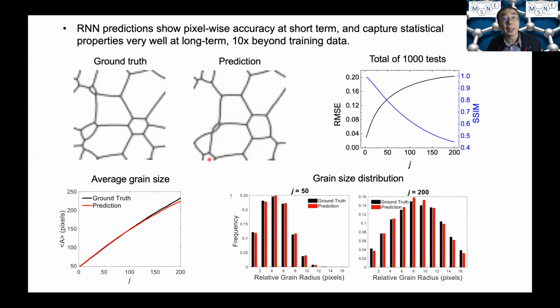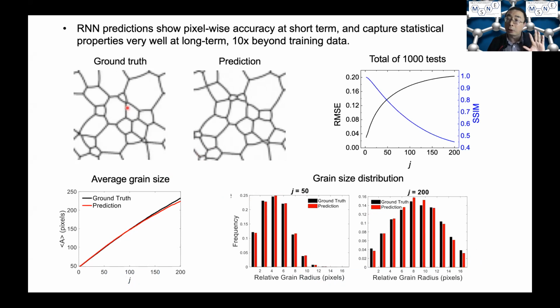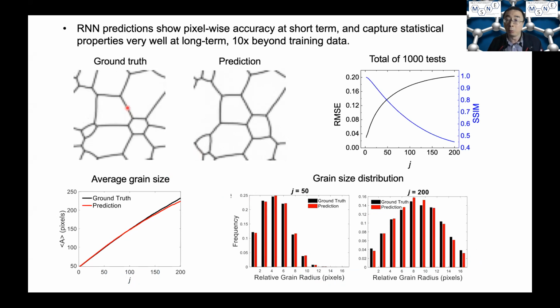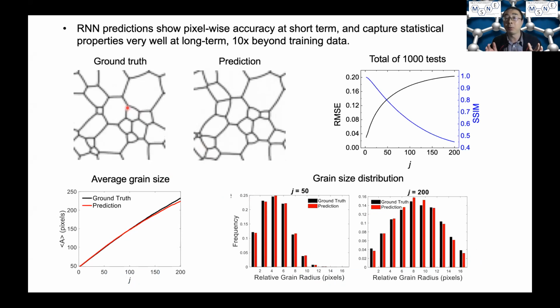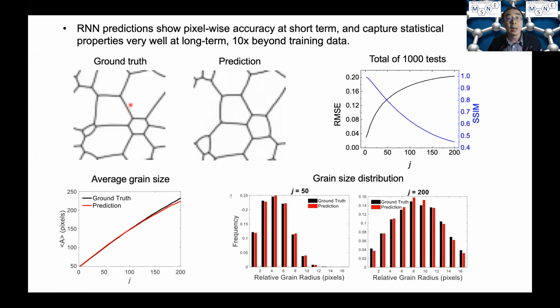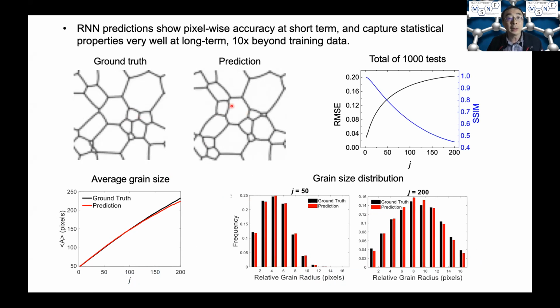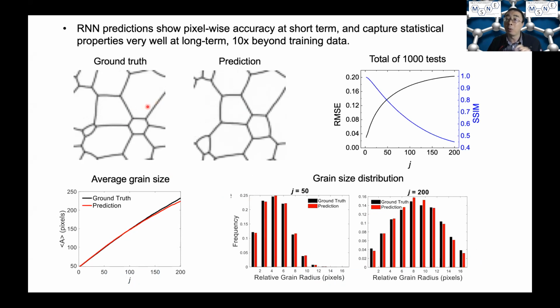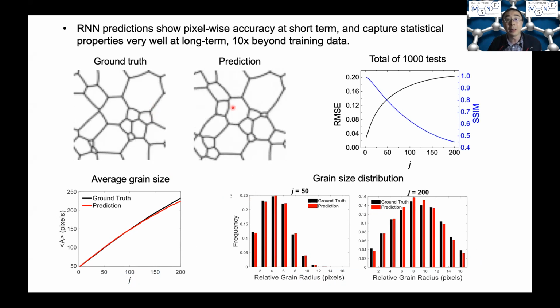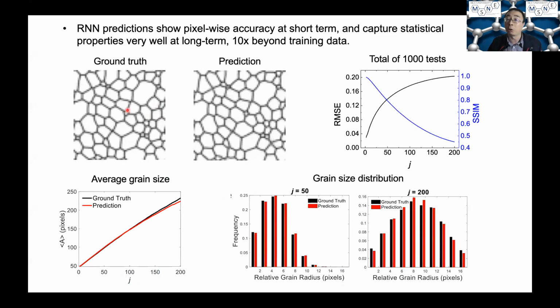What we found is that in the short term, on a time scale comparable to the length of the training clips, the prediction and the ground truth have a very good pixel-wise comparison. Visually, it's very difficult to distinguish between these two.